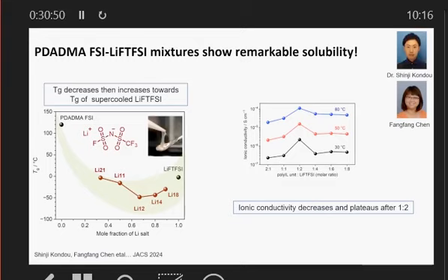So on the left-hand side, we have the Tg behavior as a function of concentration of salt. As we saw earlier on, the Tg goes down initially from over 100 down to below 0. And the 1:2, so 1 DADMA unit to 2 LiTFSI salts, and this is actually a mixed system, so it's FSI, TFSI, we see the lowest Tg, and then we see Tg goes up. And that was initially a surprise to us because we didn't have the Tg of this system. And then Shinji found that he could quench the salt into a liquid or into a glass indeed, and he was able to measure the Tg of the pure salt. It's metastable, but it can be quenched and you can get a DSC of it. And he found that was above 0 degrees. And this is why we see this parabolic behavior for Tg.